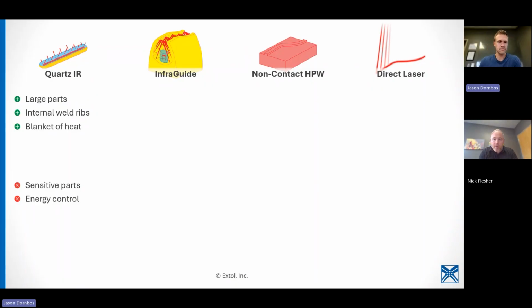I'll just say this as a general point, you'll see that we don't have specifics in what we're going to show, but our applications lab really needs to work with you on that because we've done everything from thin films to extruded panels welded to parts to manifolds, which are really rigid. Medical devices, microfluidics, really, really sensitive. This is a pretty high level webinar where we're just introducing the ideas. We absolutely want to make sure that there's no deformation or overheating of the plastic. Laser's really good if you have a very sensitive application where you can't put excessive heat into the rest of the part. You just want it at that weld rib.